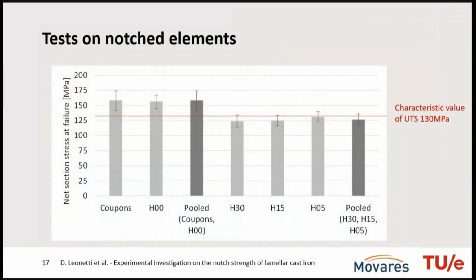So in the end, we could summarize the good test results, those that were not affected by the presence of defects. We can see that when there are no defects present, the tensile coupons have more or less the same strength as the large coupons without a hole. This is just something I can mention to you. I didn't bring the results with me, but in this case, the number of specimens that we had to reject was way larger than in the case of the tensile test. So yes, a larger volume of testing, a larger volume of material, significantly increased the chance of finding a defect. Therefore, in this case, we have to reject more specimens.